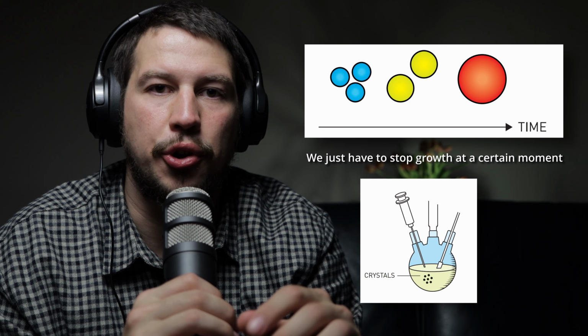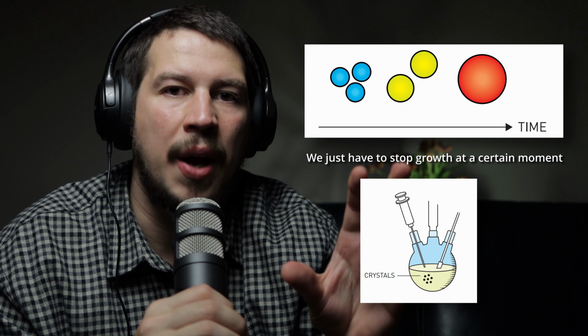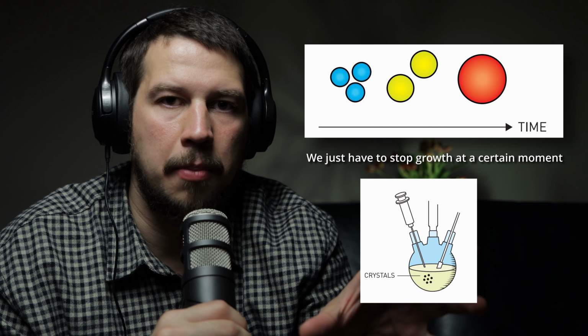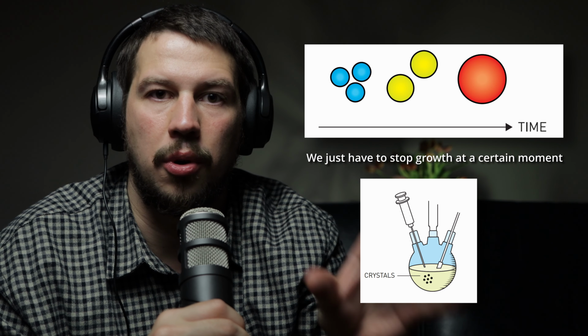So, if we make quantum dots smaller, they emit bluer light. If we make them larger, they emit redder light. And we can tune the size pretty smoothly. It allows us to cover quite a broad range of wavelengths. What's more, the brightness of the quantum dot doesn't really depend on the size. And that's exactly what is used in modern displays. We can produce quantum dots of a specific size to emit pure red or pure green light.